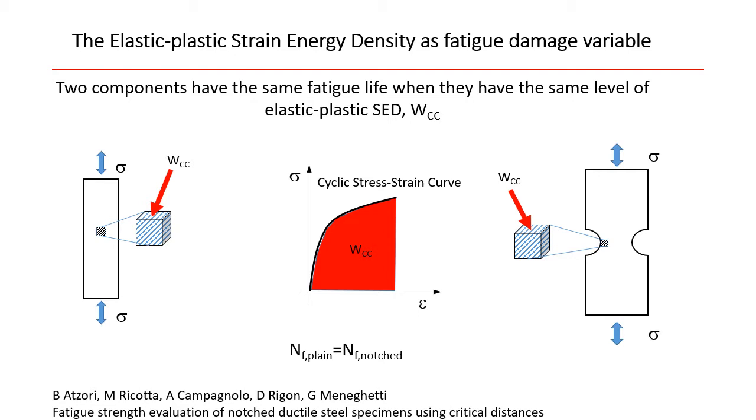Therefore, in this paper, we have assumed the elastic plastic strain energy density as the fatigue damage variable, and therefore we can see that two components have the same fatigue life when they have the same level of elastic plastic strain energy density, here named as WCC.